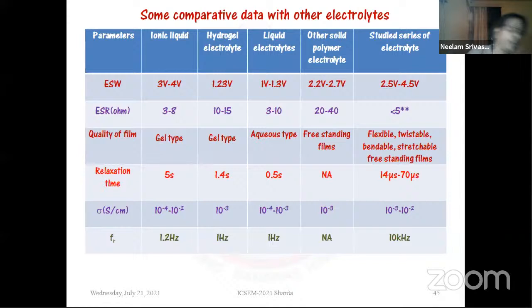So at the end, if we try to summarize our values and compare with other available electrolyte systems, we can compare it with ionic liquid, hydrogel electrolyte, liquid electrolyte, and other solid polymer electrolytes. Of course, the ionic liquid shows the best ESW. The electrochemical stability window is very wide, 3 to 4. But one should remember that ionic liquids are very costly systems. So when it comes to commercial application, it is always a question how to use it. Our system has shown 2.5 to 4.5, along with cost effectiveness of the system. So this is a really very encouraging result which we have observed.